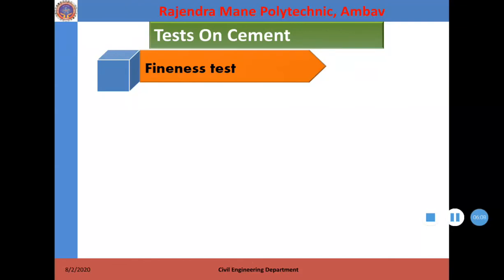The disadvantage of fine grinding is that the cement is susceptible to air set and easy deterioration. The maximum number of particles in a sample of cement should have a size less than about 100 microns. The smallest particles may have a size of about 1.5 micron. By and large, an average size of cement particles may be taken as about 10 micron.